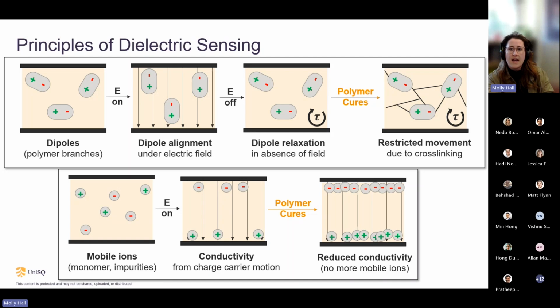As you continue to cure, your material starts to cross-link and it freezes things into place. So your dipoles have a much harder time relaxing and aligning, and eventually they stop moving entirely. And your mobile ions get depleted or they get frozen into place and they can no longer move. So this is really the principle of dielectrics for thermoset monitoring. We're seeing how these electrically charged particles are getting frozen through the cure, and that's allowing us to monitor what's happening in the cure.